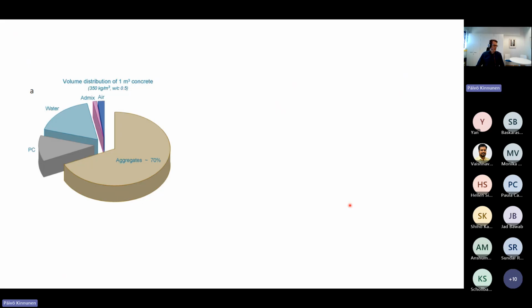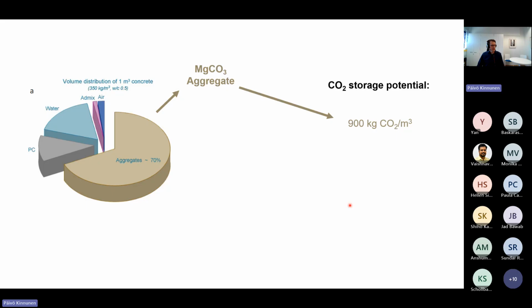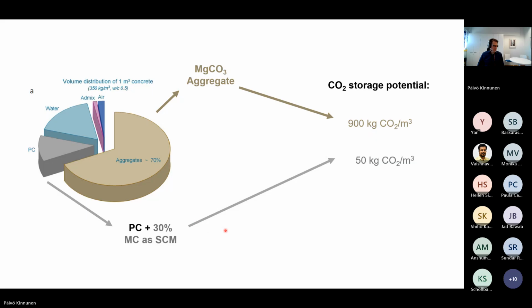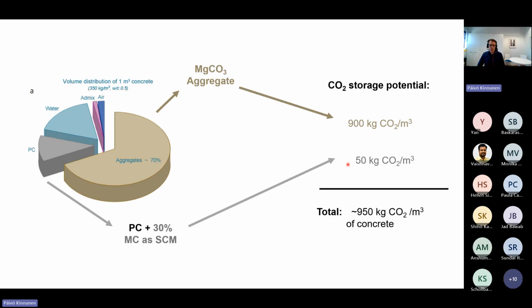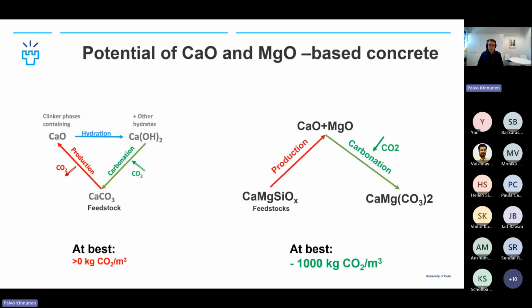But here, if we just look at the volumes that are possible, if our aim is to use magnesite as aggregate, we could take, in theory, the magnesium carbonate aggregate, and then we would store something like 900 kilos of CO2 per cubic meter, and then we have the Portland cement, and then we could add magnesite as supplementary cementitious material, but that would result in much less CO2 reduction or storage in this case. So you can see that by far the most CO2 storage potential is in the aggregates. And so this is why we're thinking about that. Well, actually, let me just skip ahead for a little bit.